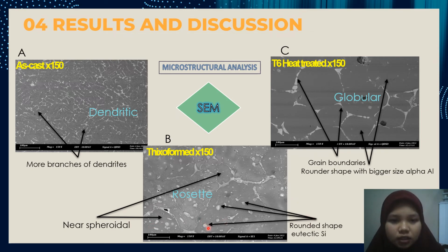And we can see that there are many rounded shapes of eutectic silicon. And for figure C, the T6 heat treated, it has formed a globular shape, with grain boundary formation in between the grains, and a rounded shape with bigger size of alpha aluminium. So we can see a much more globular shape.